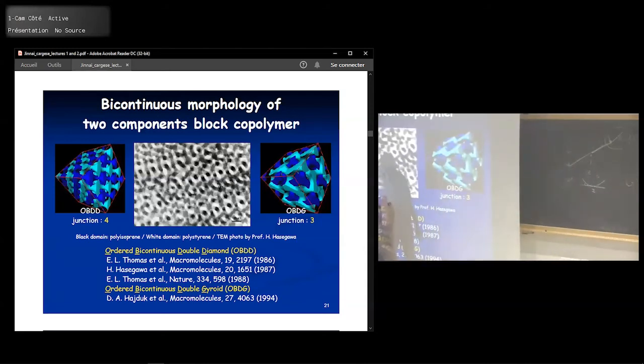This model, the ordered bicontinuous double diamond structure. There's a minimal surface called the diamond surface, and that divides the space 50-50. Then this picture is made like this: if this is the minimal surface, then we make a parallel surface up and down. So you have two surfaces, and then you measure the volume fraction. The volume fraction of this network phase is something like 33%, 34%, which is the polymer fraction where we observe gyroid. Then we stop traveling the parallel surface and fix it. That's how we make this type of image, model.